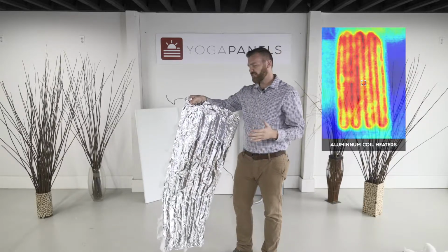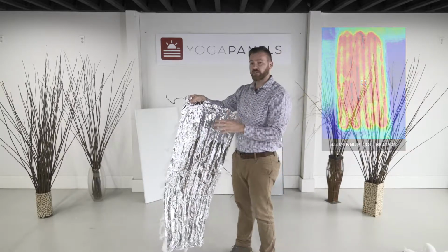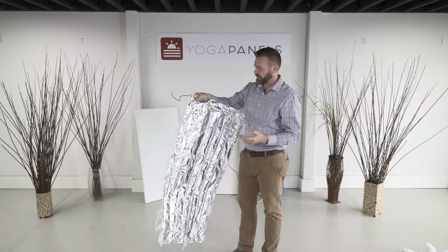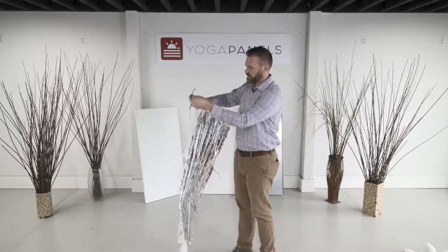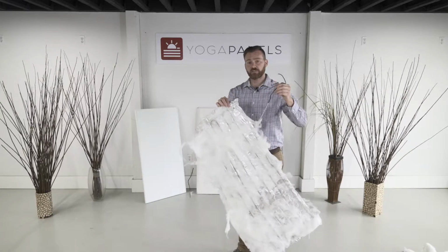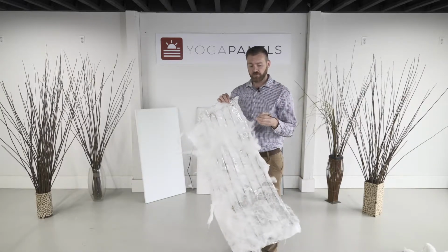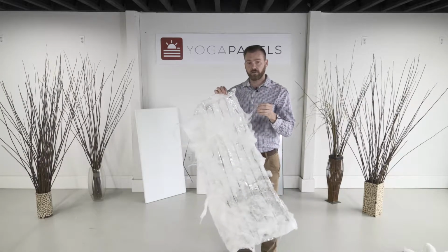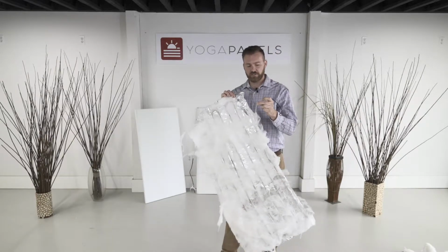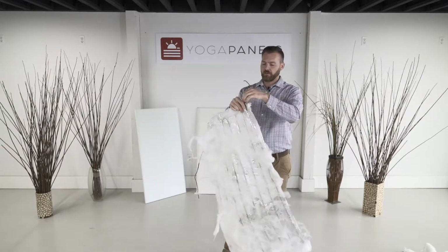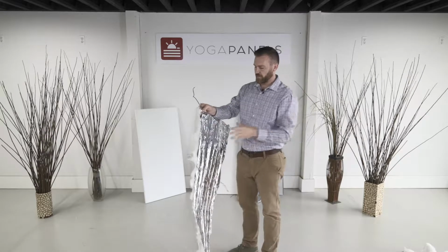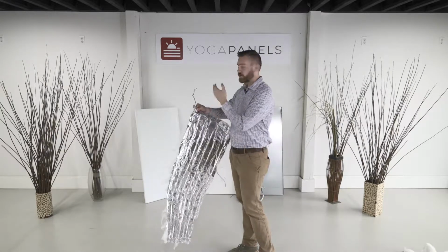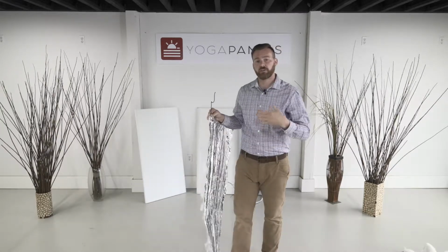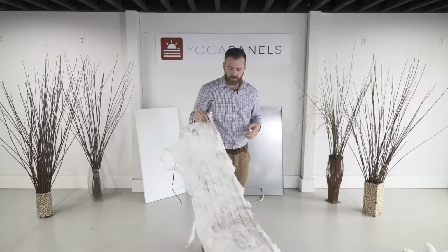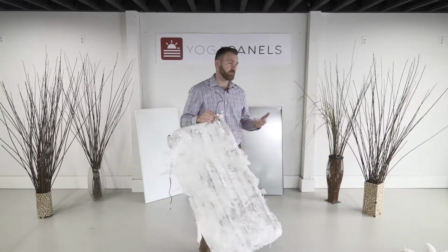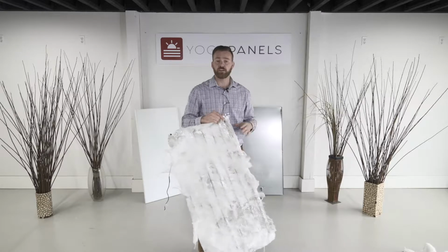So you get about 70–80% of your heat coming forward and 20 to 30% of it being lost out the back. And also, if you can see, you really only have about 10% of this panel that's producing heat. And it's producing a really high amount of heat off this coil. This coil actually gets almost red hot. And the theory is that the heat produced from this thin coil will filter through the ceramic and give you an infrared wavelength. And it does. It works well for what it's designed.